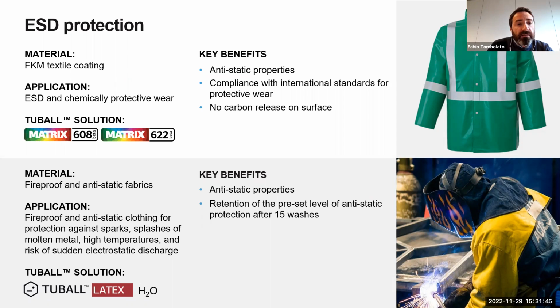Fireproof antistatic clothing for protection against spark can be obtained using, for example, our TUBALL Latex to achieve antistatic properties. As I told you before, graphene nanotubes bring properties that are stable over time and over the entire life of the material. And in this specific case, the antistatic properties were maintained also after 15 cycles of washing.